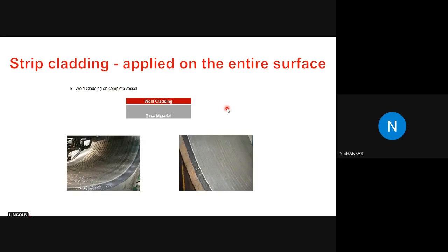Initially, they started off with wire cladding, because in welding we use MIG wires and submerged arc wires. So we started off using wires for cladding. But you want to lay over such a big area, and it's going to be a time-consuming process. So people moved on to strip cladding, where instead of a wire, a strip is used. It could be a 30 mm, 60 mm, 90 mm, or 120 mm strip with 0.5 to 0.7 mm thickness, used to overlay the inner walls of pressure vessels. That's called strip cladding.